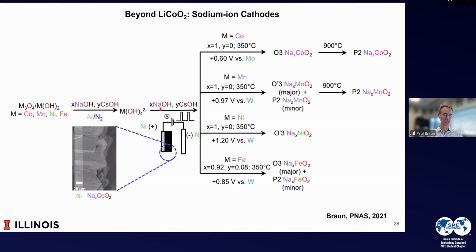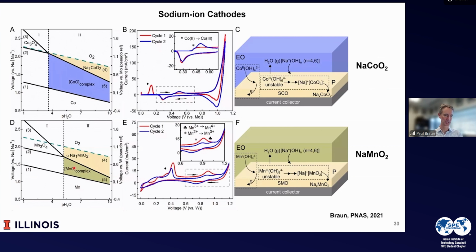Overall, the system looks quite similar. Here, we're just using a bath of sodium hydroxide and cesium hydroxide, so a little bit different bath chemistry, but the same concept. And the Pourbaix diagrams are shown here. And so indeed, there is a stable region of sodium cobalt oxide, sodium manganese oxide. The electrochemistry is a little bit more complicated. And so when you cycle, for example, there are multiple peaks, there's some irreversible phase transitions. But again, what we see here is that indeed these materials cycle and can be electrochemically deposited.